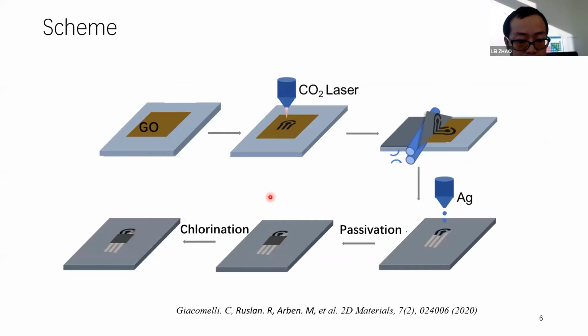So how do we make the electrode? This work was developed based on previous work done in our group. Basically, we first form a graphene oxide film on the substrate, then use a laser to reduce it. After applying pressure, we can selectively transfer the rGO electrode onto another surface. Following this, we use inkjet printing technology to produce the connections. Then after the passivation, we chlorinate the silver to form a pseudo-reference electrode.